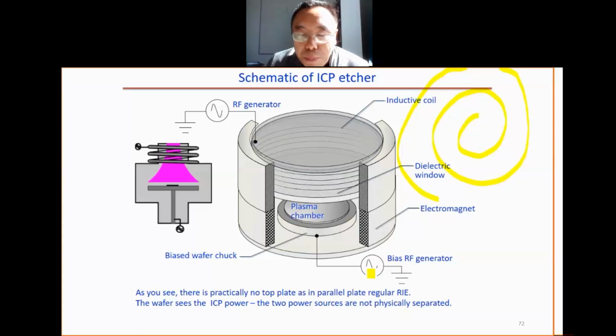Then there is the bias power. This gives you the energy for the ion to bombard, how many electron volts the ion has when bombarding the sample surface. So this determines the physical bombardment, and the coil power determines the number of the ions. Here you can see this is the bottom electrode. You don't see the top electrode. Actually, the entire thing will be considered as the top electrode for this parallel plate. The bottom one is the parallel plate, the bottom one.